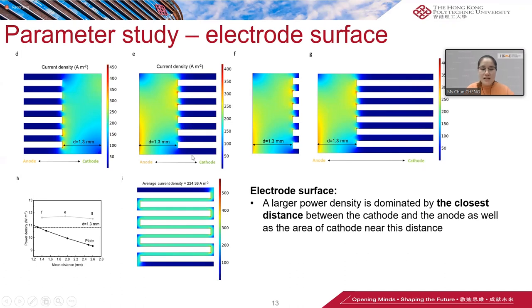So as a result, the ribbed cathode works under a current density of around 200 ampere per meter square and power density of around 11.7 watt per meter square, which is slightly higher than those of plate electrode. The finding lends support to our assumption that the power density is hindered by the relatively low kinetics of the cathode electrode. So consequently, enlarging the cathode area in our research, the cathode electrode, is more efficient than improving the anode.